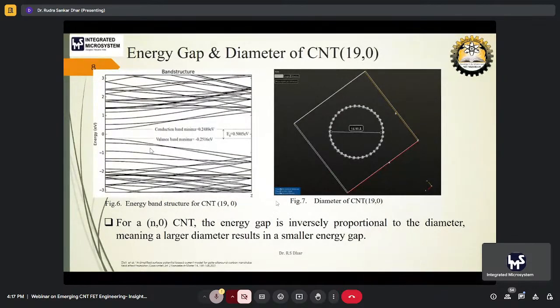So this is the picture of a band structure. As you can see, in this case we have chosen the N0 option for 19.0. So with the 19.0 option, this is the band structure and this is the diameter of the CNT that we get, which is 14.9 angstrom. That is the total diameter of the tube with the 19.0.